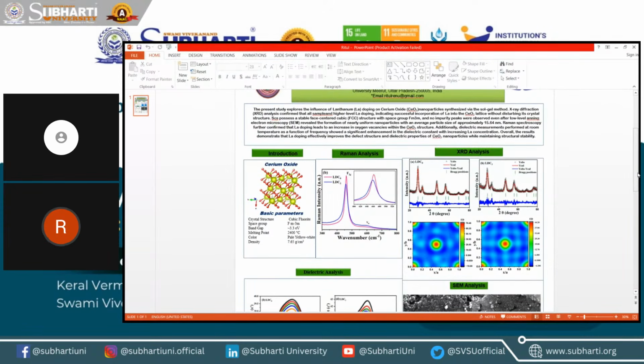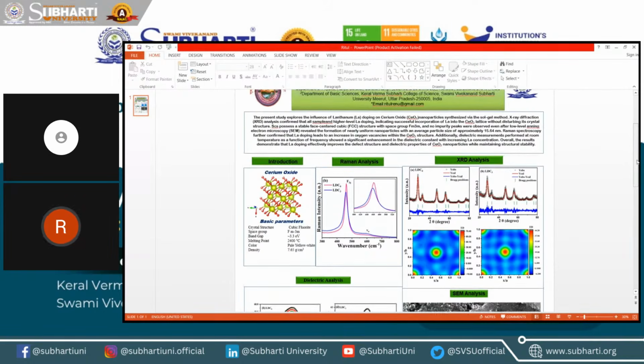Now the XRD analysis: XRD confirms the pure cubic phase of CeO2 with no impurity peaks, indicating successful La incorporation; peaks slightly shift with doping, showing lattice modification. Now the Raman analysis: a strong F2g peak is observed, and with La doping the peak broadens and slightly shifts. This indicates an increase in oxygen vacancies and structural disorder.